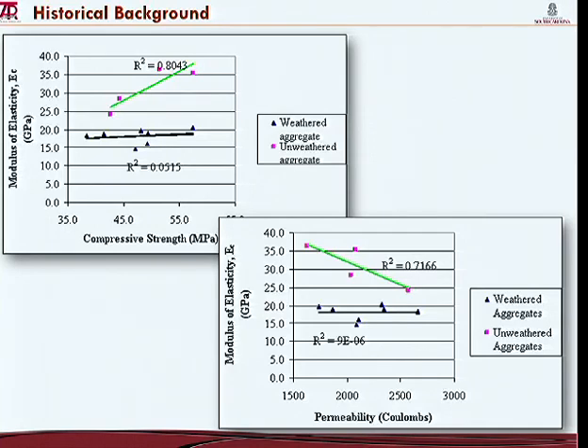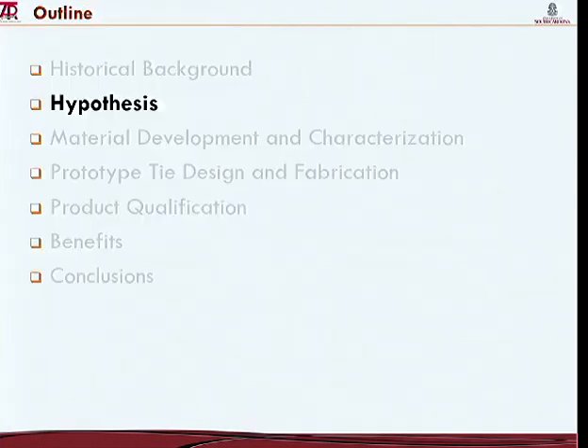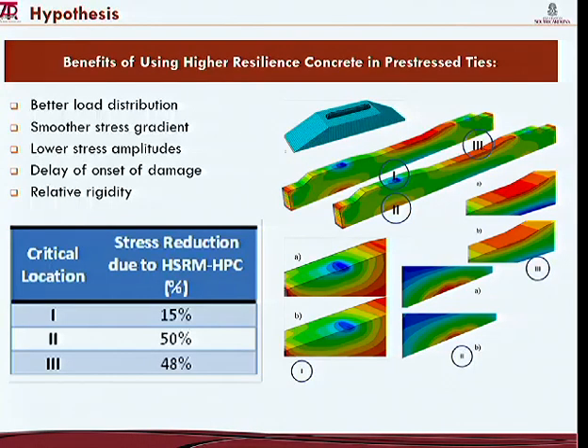Correlation of the modulus of elasticity to the permeability, again, no correlation for weathered aggregates, and correlation as expected for the healthy material. So the hypothesis is that if we use such a material with a high strength but reduced modulus in a concrete tie, then we will be able to get a better load distribution within the tie. We'll get smoother stress gradients because of the higher flexibility, lower the stress amplitudes, delay the onset of damage, of cracking in that case, and improve the relative rigidity between the ties and the ballast.